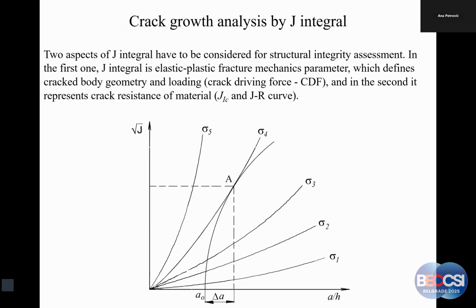So first, to remind you about the J integral, from one of its aspects, which is common for fracture mechanics parameters. From one side, we treat them as a material property, and this is represented here by the JR curve. You can see it here. And this is to be measured. And from the other point of view, we can interpret J integral as crack driving force. And these are crack driving forces for different levels of stress, of loading. And we calculate that. Could be measured, but it's tricky. Basically speaking, crack driving forces are calculated, and material property J curve are measured.